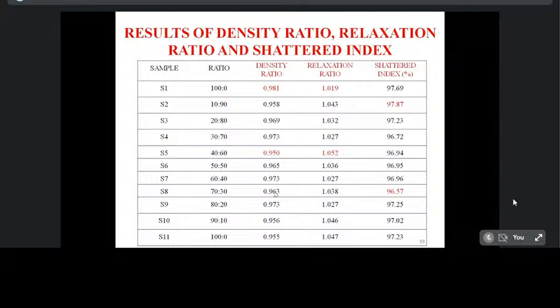So a value greater than 90 is achieved as a good quality shattered index for the produced biomass briquettes. Here all the produced biomass briquettes have more than 95. The minimum value was achieved for sample S8 with its mixed ratio of 70:30, with a shattered index of 96.57, and 97.87 is the maximum shattered index, for sample S2.